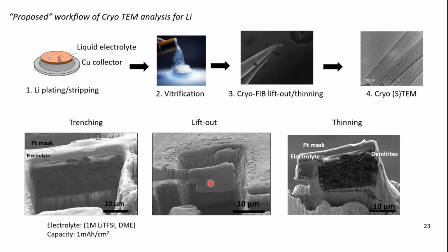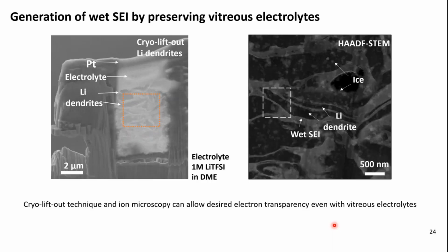And in the cryo-FIB microscope, this is how vitrified electrolyte and lithium dendrite look. You can trench the sample with the preserved liquid electrolyte. You can perform lift-out and thinning until you have the desired electron transparency. This is one STEM image when I prepared cryo-lift-out samples with vitrified electrolytes. You can see the dark contrast from lithium and the bright contrast coming from frozen liquid electrolyte.